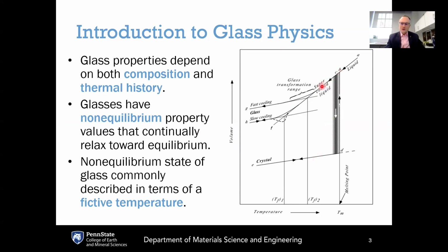Now, the supercooled liquid, if you were to continue to cool that, the viscosity of the supercooled liquid continues to go up, and eventually the time scale of the flow of the supercooled liquid becomes very slow compared to your observation time scale. And when that happens, the supercooled liquid undergoes this glass transformation or glass transition. This is not a thermodynamic phase transition. This is a kinetic transition due to the kinetics of the supercooled liquid becoming slower and slower.